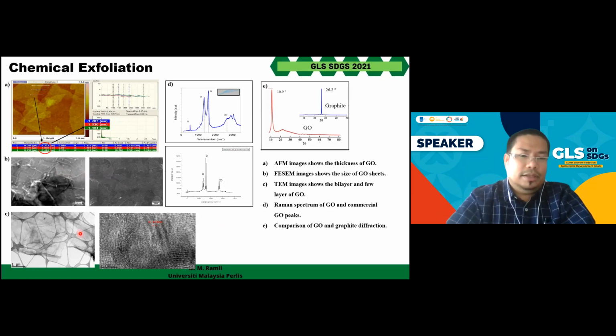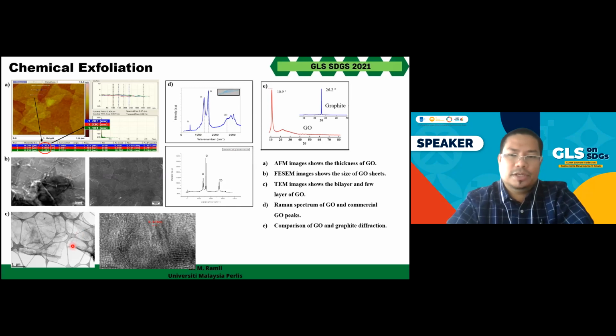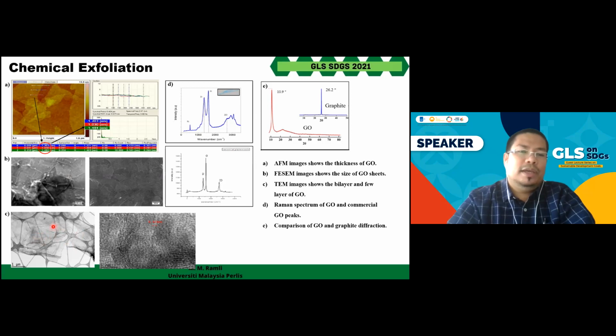And then we did the TEM, the transmission electron microscopy images, where we have some of the layers folded. For example, here, folded. Some of the layer here is a very thin layer, which is less than 10 nanometer. And then some of the area here is more than 1 nanometer. So we believe this is more than one layer. And we presume this is 3 to 4 layers because the thickness is around 5 nanometer.